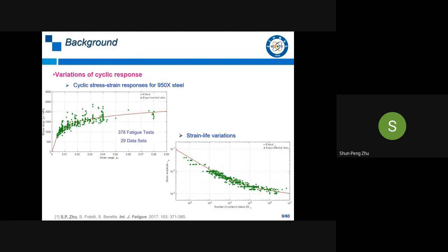Here I give you examples of the scatter or variations of material properties. Here we have two plots. The first one is a cyclic stress-strain response for the 950X steel, which is a car steel. Here we have nearly 378 test samples, and we can see that along different strain ranges it shows different stress responses, and also a larger scatter. For the life response, we can also see that for a given strain amplitude or stress amplitude, it leads to scattered life. The scatter in life is, for this level, more than 10 times.